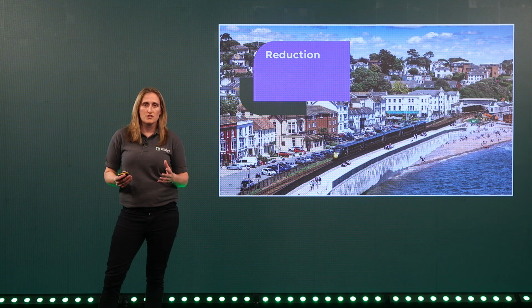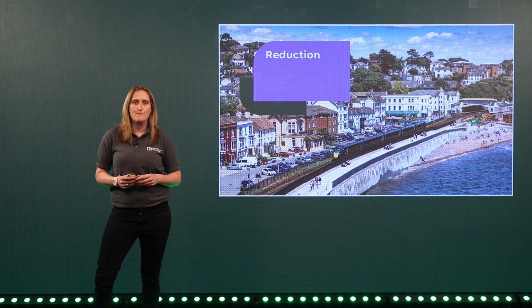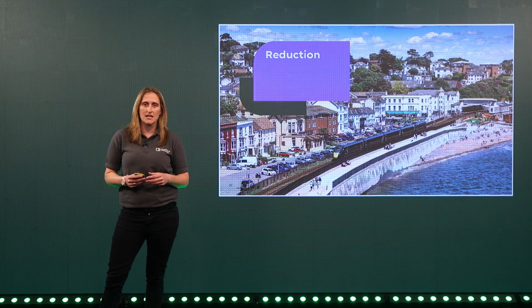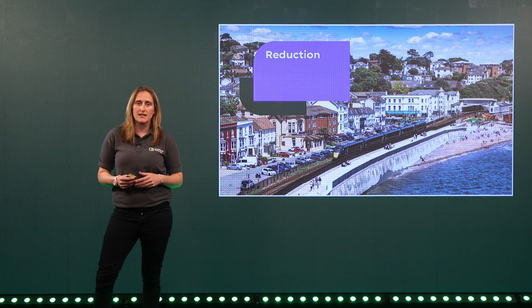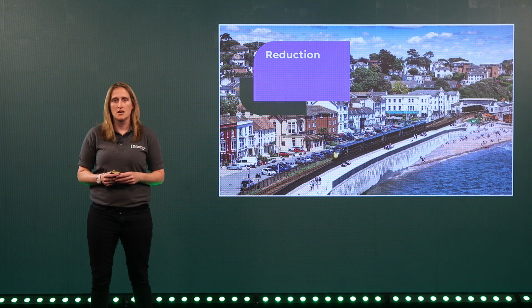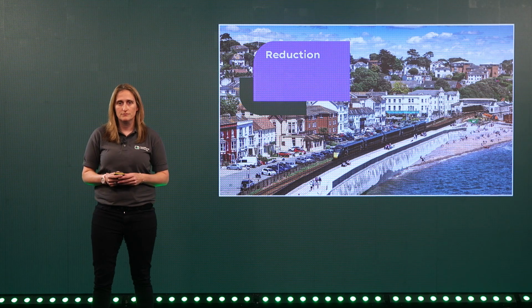By using 1 tonne of Regen in concrete, this reduces the embedded CO2 emissions by about 900 kilograms compared to using 1 tonne of Portland cement. Another example of developing products with reduced CO2 emissions is calcined clay. If this is substituted for the energy-intense clinker, by using calcined clay as a clinker substitute, in principle, could provide a CO2 reduction of up to 40%. This will allow us to significantly expand the range of low carbon products we have available.